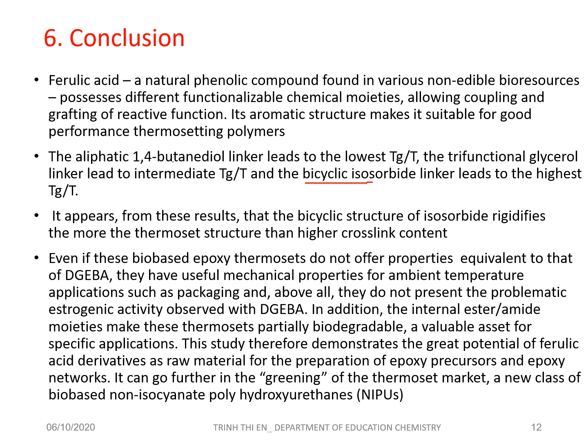it appears from the results that the rigid bicyclic structure of isosorbide rigidifies the thermoset structure more than a higher crosslink content. As we know, the bicyclic structure does not have a high crosslink density, neither does glycerol in the structure, but it has a higher glass transition temperature. Even if these bio-based epoxy thermosets do not offer properties equivalent to those of DGEBA, they have useful mechanical properties for ambient temperature applications such as packaging, and